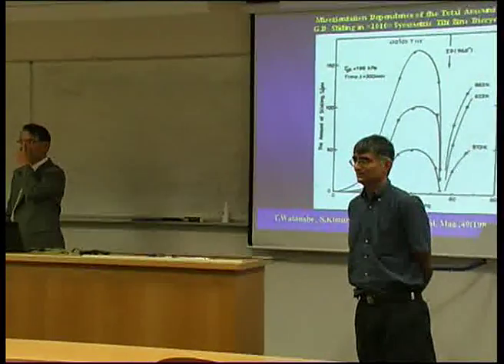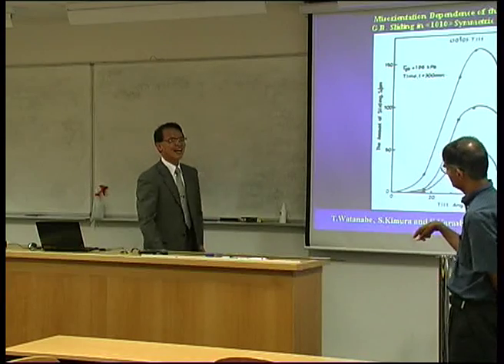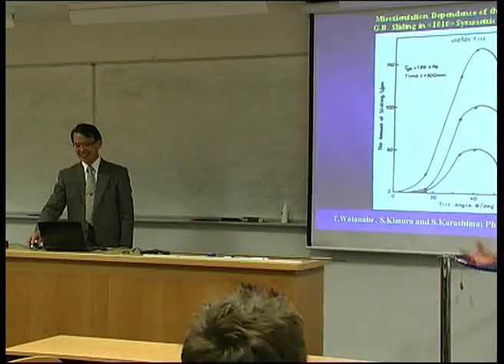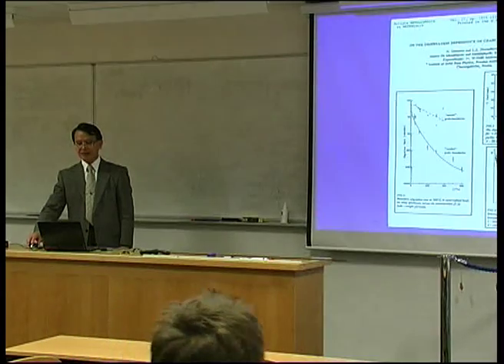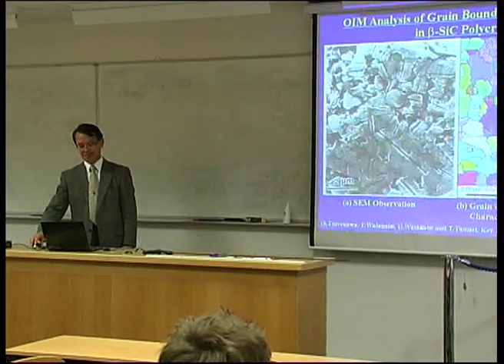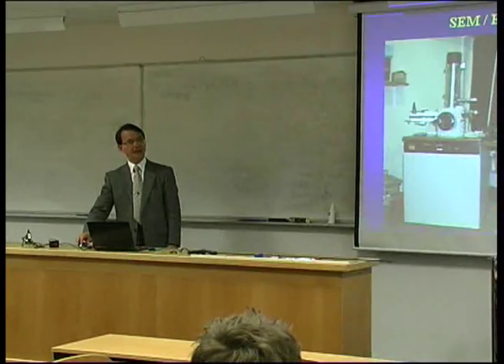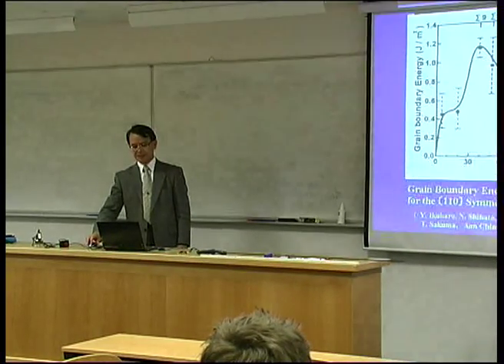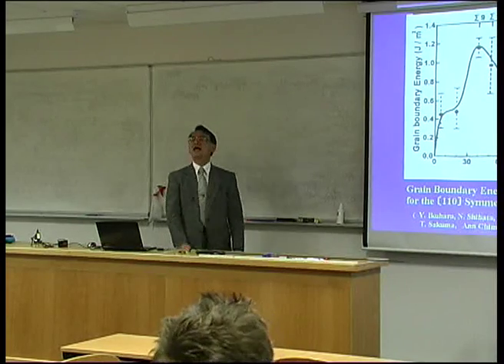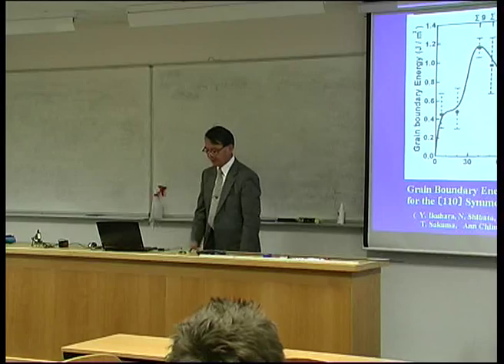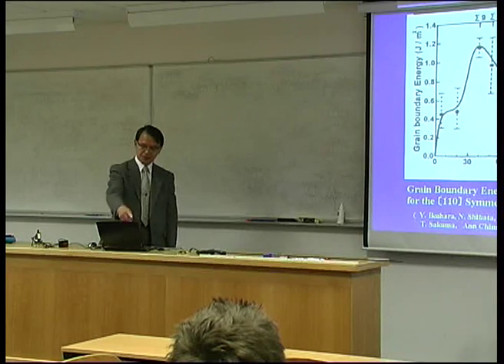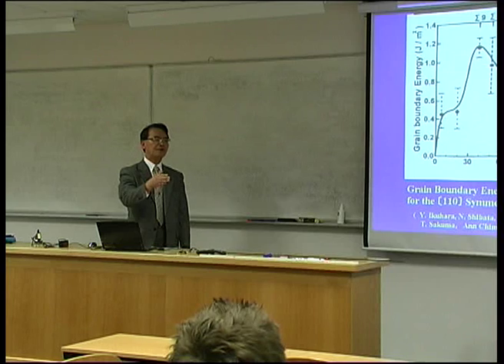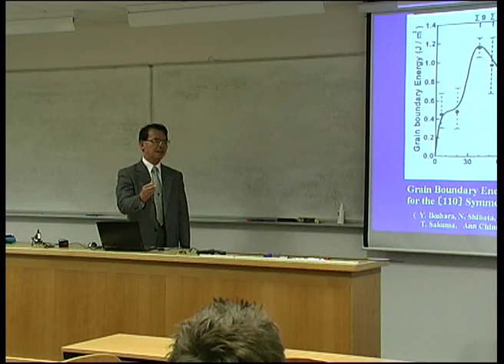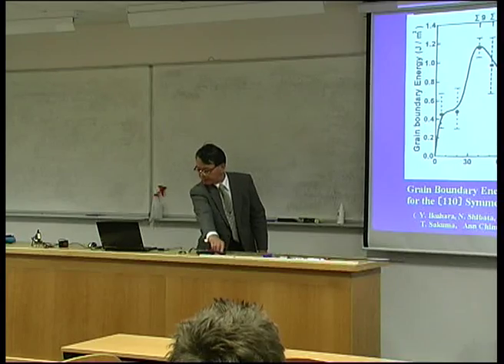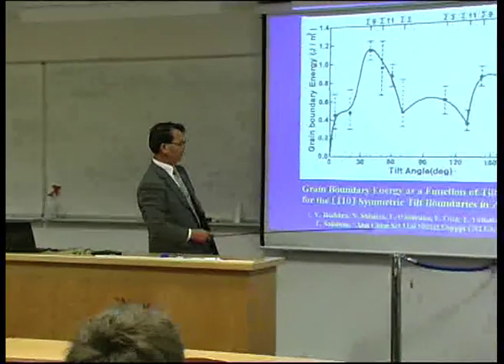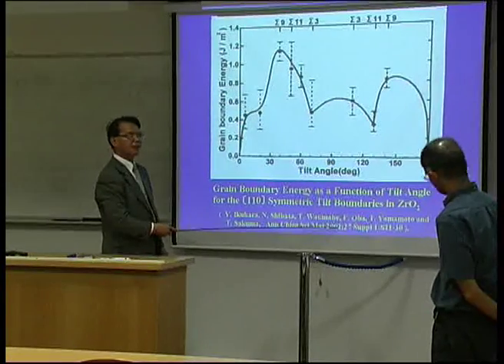More questions? I have one. You have your plot of energy versus sigma for the zirconia. How do you actually measure the energy? They use a bicrystal sample and dihedral angle measurement. But you need a reference value? Maybe I should check. Here you have absolute values? This is relative to a twin boundary, I think. Anyway, they published it in a special issue of a French journal, which I edited.